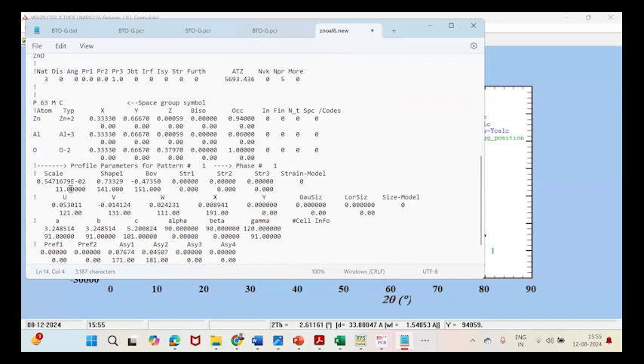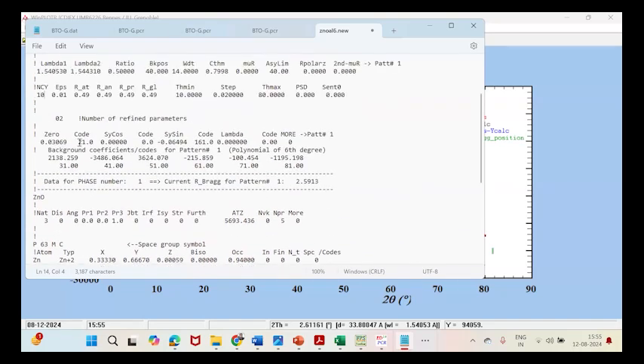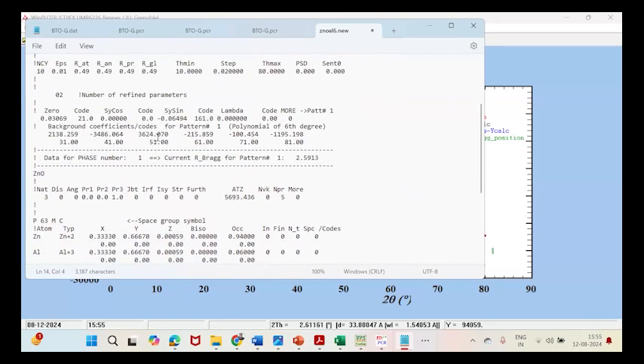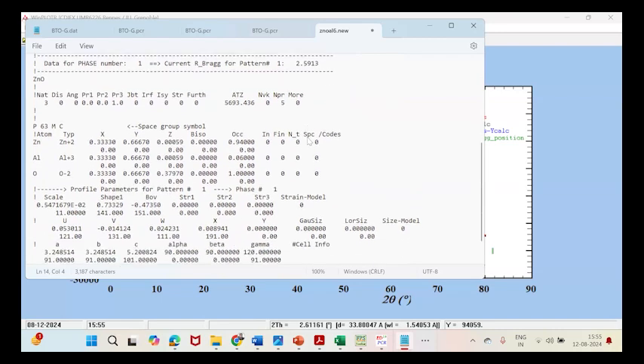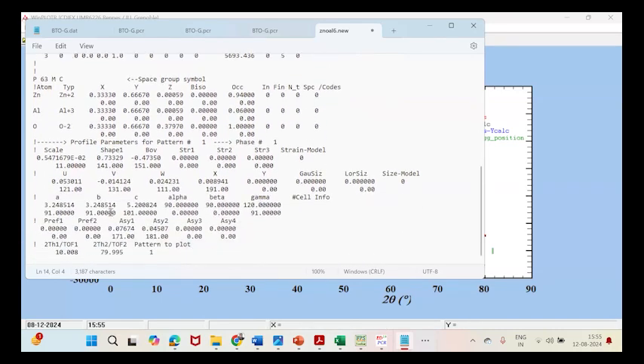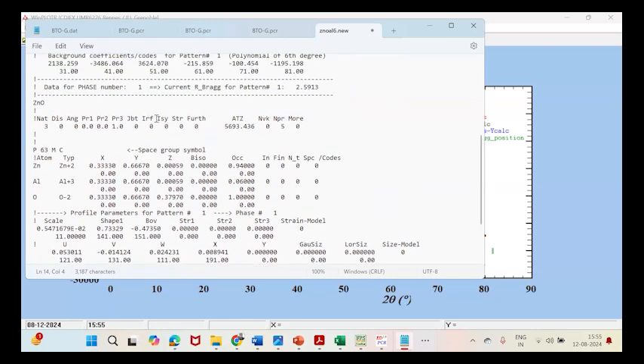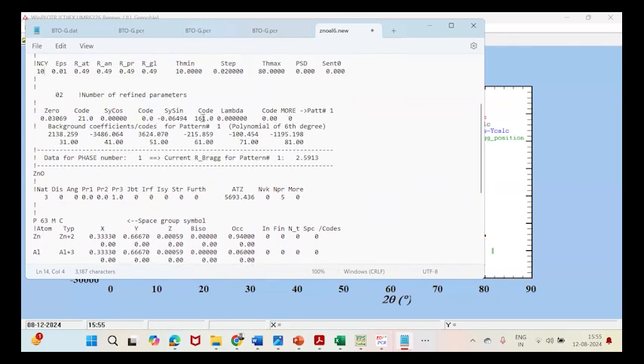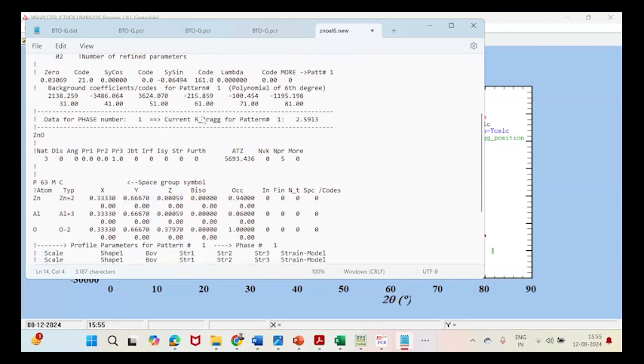0, first one is the scale, then 0, then 3, 4, 5, 6, 7, 8 background. Then since it is a tetragonal system, the 9 and 10, then W 11, 12, 13, shape 14, and overall temperature factor is 15. Then this is the instrumental error, 16. If any transparency or the sample is not kept properly, then this will take care of that thing.